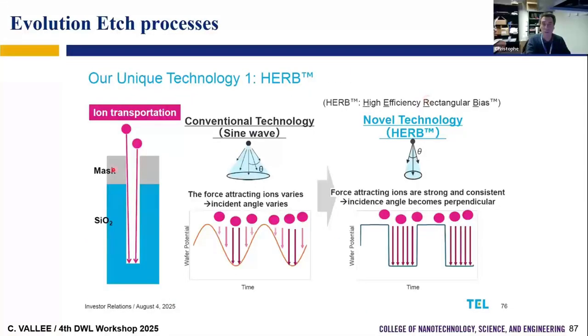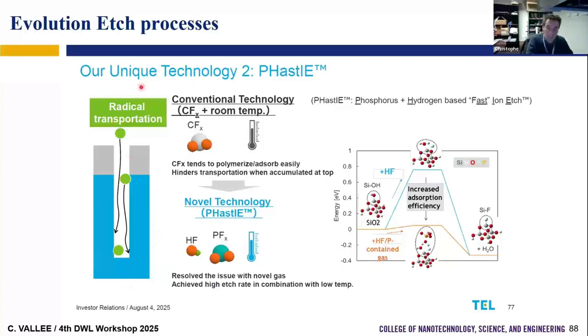For example, they have to develop new equipment where they can go from RF bias to pulse square bias. As I said, it's what they call the HERB for their technology. Because if you have this pulse DC, we have only energetic ions. If we have RF bias, we have low and high energetic ions. So the low energetic ions have a large ion angular distribution. Only the high energetic ions will come to the bottom. If we have a DC pulse, we have only energetic ions, so they all come to the bottom. So we try to remove this distribution to come to this one, to remove the low energetic ions that will not go to the bottom. And we try to improve our high aspect ratio with radicals.